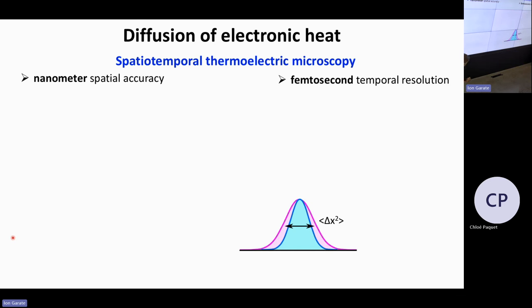So the diffusion process can be seen as follows. You dump particles or energy or heat, whatever you want, in, let's say, a Gaussian spot. Then if you wait as a function of time, you will see that this Gaussian spot will be broadening. And this broadening will be governed by a diffusion coefficient, the diffusivity, that is linear in the square of the width of this Gaussian pulse.